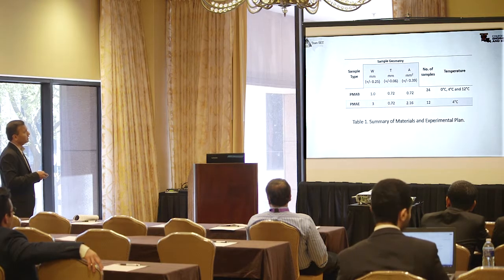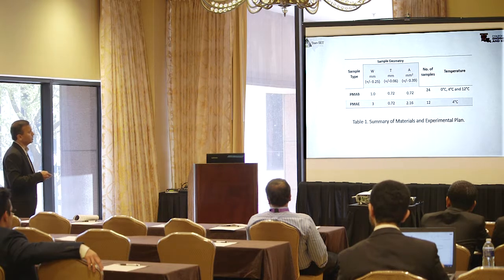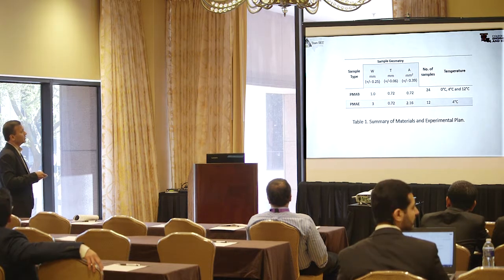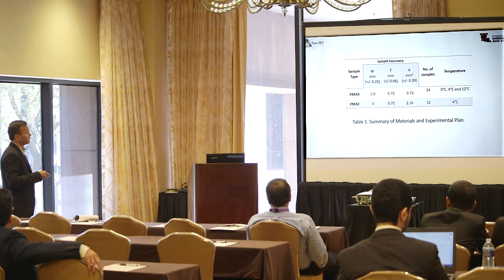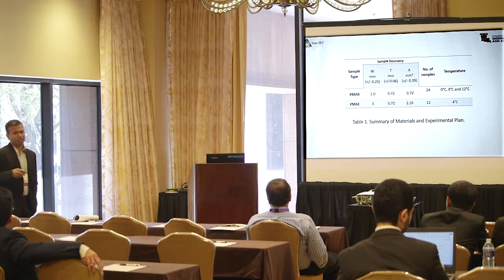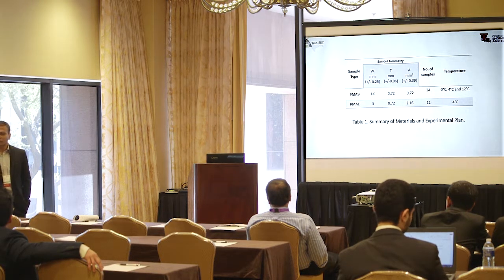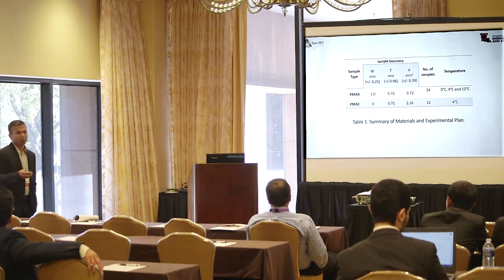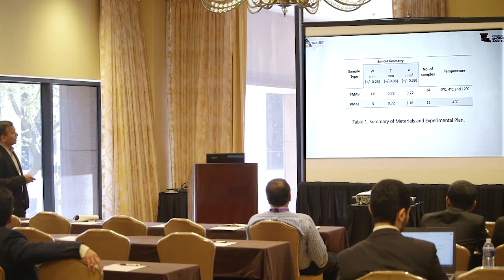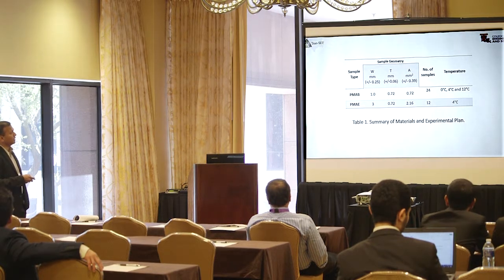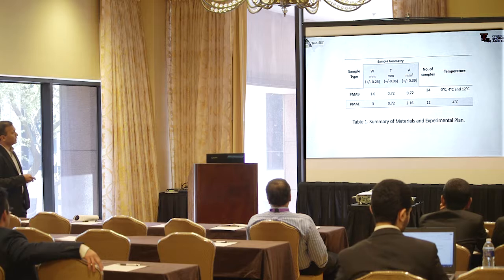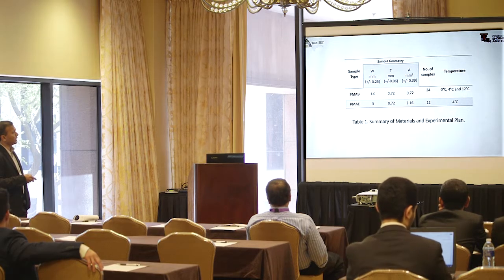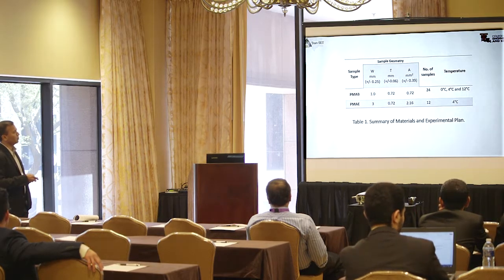Width is 1 millimeter, and then thickness is 0.72 millimeters, so the area is 0.72. And then we change that with the polymer modified asphalt emulsion, where the width is 3 millimeters. When I say polymer modified asphalt emulsion, I do mean the residue of the polymer emulsion. So this is the area here, this is the area here, and the number of samples is 24, and here 12 samples we used.